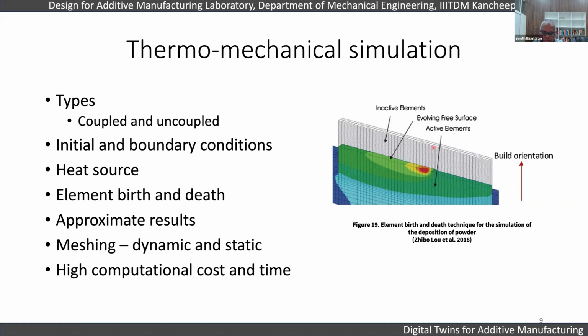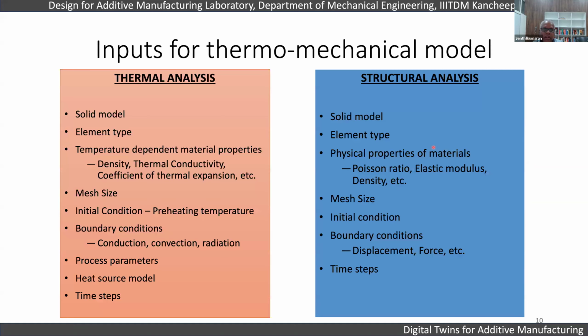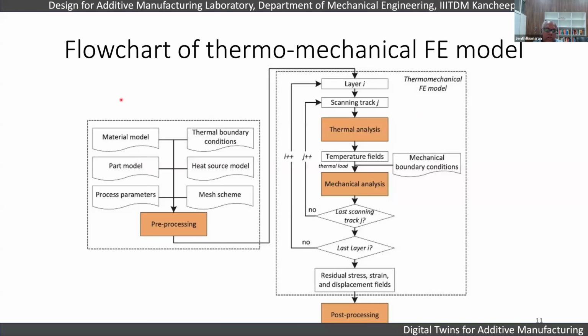So normally what happens is you input the solid model, element type for the thermal analysis, you input the density, physical properties, thermal properties. Here you input the mesh size, conditions, boundary conditions, process parameters. Here displacement, force; here the boundary conditions are convection, and the heat source model is used here to basically do the thermal analysis. So this is how it is done. Normally you take a material model, part model, process parameters, boundary conditions, heat source model, and a scheme, whether dynamic or static mesh scheme.